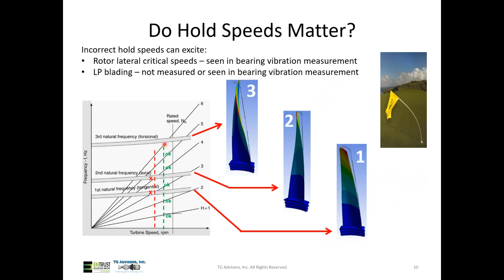Well, the same is true for hold speeds. So if I look at this line where I say okay, the green line, I'm still good. If I'm holding at that speed, I don't have any resonance predicted on the blade. But if I were to back up to the red speed and I held there, 3 times running speed would be resonant with my first natural frequency.